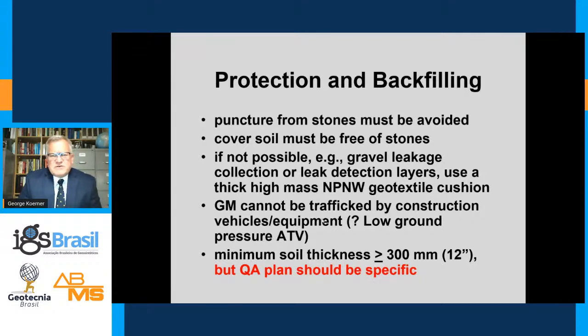If possible, the gravel leachate collection and removal system has to be separated from the geomembrane with a heavy needle punch non-woven or a puncture protection material. Geomembrane also cannot be trafficked by construction vehicles. There is some discussion around low ground pressure ATVs. This has to be agreed on, though, prior to the job.